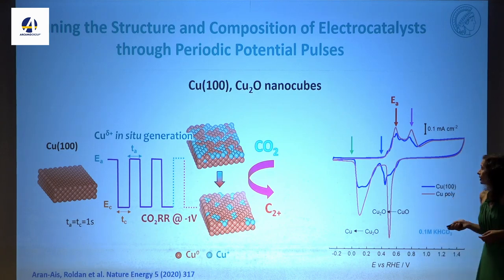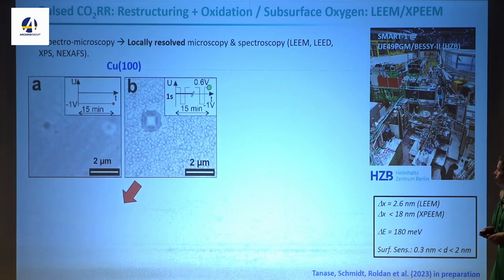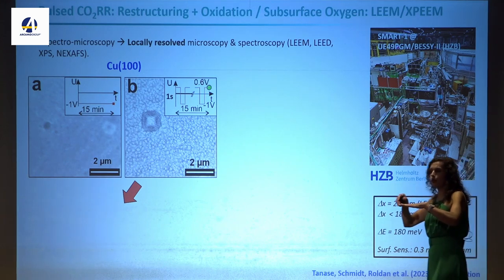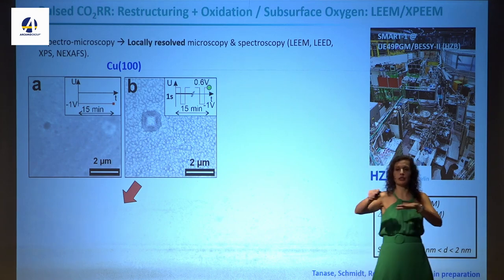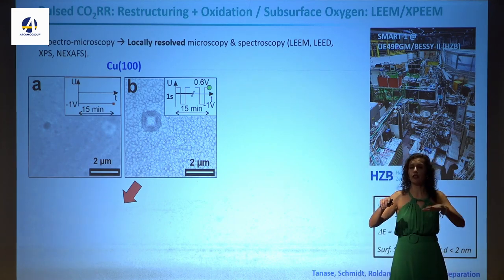And when we do this, we wanted first to see, do these applied potential pulses restructure the surface, not just change the oxidation state? Again, we have our synchrotron beamline here, and we can do microscopy and spectroscopy simultaneously. This is a copper 100 surface, again, a very flat single crystal. And you do CO2 electroreduction for about 15 minutes. The surface looks flat. Unfortunately, here we do quasi in situ. We have the electrochemical cell attached to the microscope, and we transfer without air exposure.